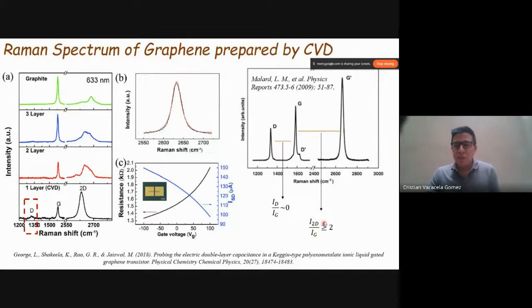So if we take the ratio between the intensity of the 2D band over the G band, and this number is greater than 2, you are working with a single layer graphene. Here, for example, the authors call this band the 2D peak, while other authors use another name for the same vibration mode, the G prime peak. These are just two different notations, but the bands are the same thing. Just remember this ratio if you are working with the Raman spectrum to identify different materials.